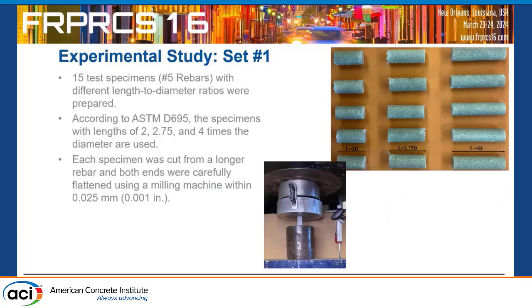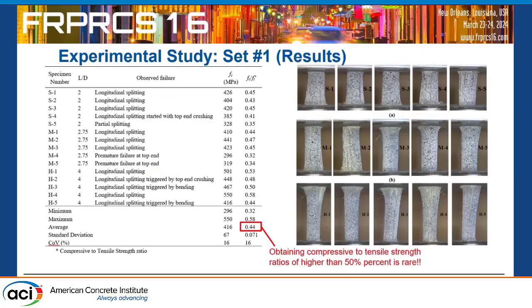So we need to consider this. We have 3 sets of tests. The first one is ASTM D695 to see how it works. Just putting the bare FRP bars between two plates. We tested L over D, length over diameter, of 2, 2.75, 4, and 5, for each one to see how it works. And here is the summary of results.